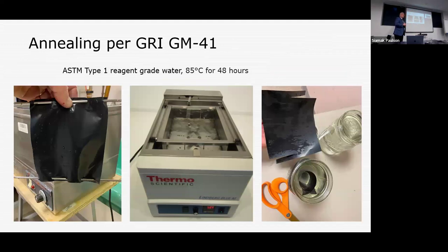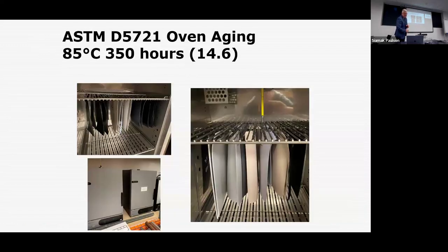You will then take that film and anneal it. This annealing process uses reagent grade water, very clean water, at 85 degrees C for 2 days. You will anneal that material, and now you will do the exposure on that material. And there are 3 exposures. The first one is oven aging that you're very familiar with at 85 degrees C. You're doing it for about 15 days, 2 weeks. And you have the OIT at time 0, and you're going to compare that with OIT after 350 hours or 15 days.